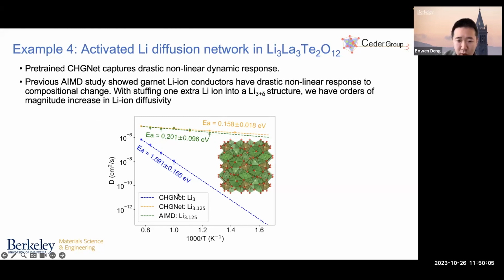So the pristine structure has a composition of Li3 LATO, while we put a small amount of lithium excess into this framework to have a Li3+δ LATO material, and we simulate the diffusivity of the lithium ions in this molecular dynamics simulation. And what we found is that CHGNet correctly recovers this diffusivity, first of all, at the pristine structure, where the green curve is the AIMD result and the yellow curve is the CHGNet result. And we match the diffusivity of the unstuffed structure and significantly decrease the error bar that's given by AIMD.